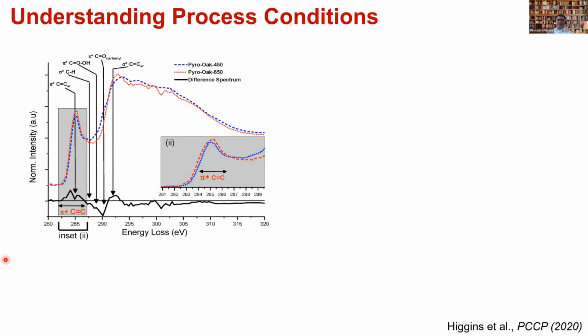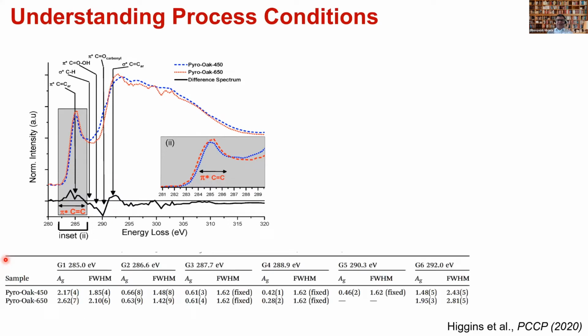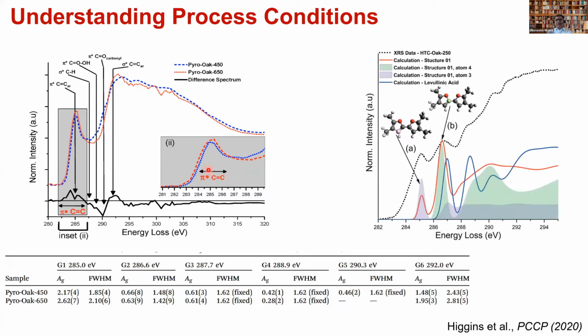So here is something that you see: oak pyrolyzed at 450 degrees Celsius versus 650 degrees Celsius, and you do see that there are differences. A, at 650 you have more graphitic component, this resonance, and also B, you see the broadening of this peak at 650 compared to 450, and this relates to basically the carbon backbone that you have. We also conducted X-ray Raman on HTC material, and don't ask me this.